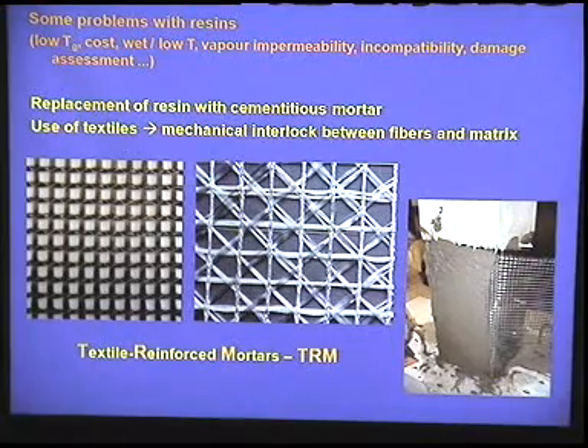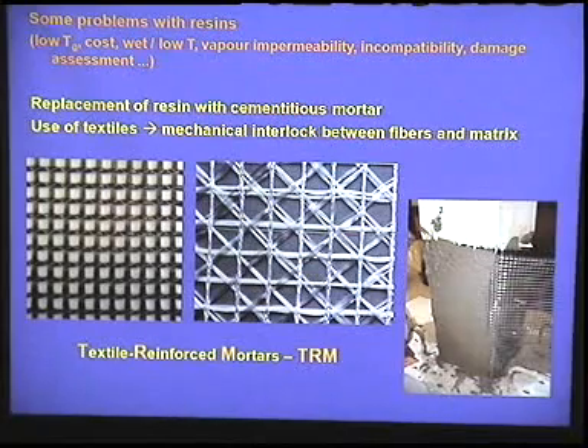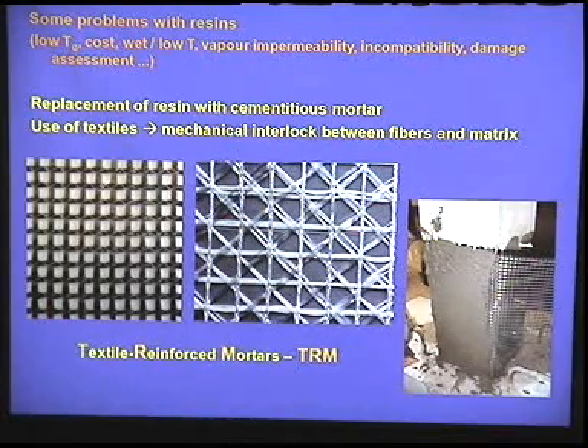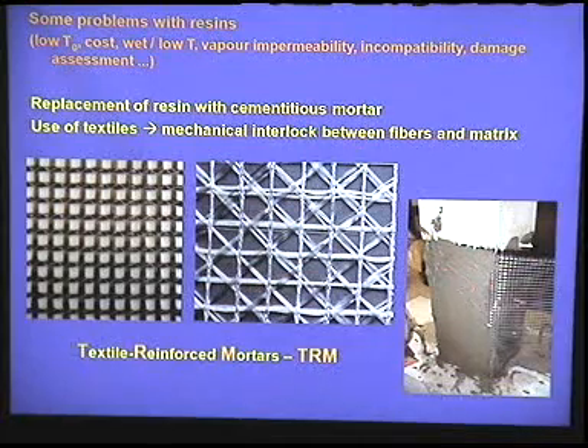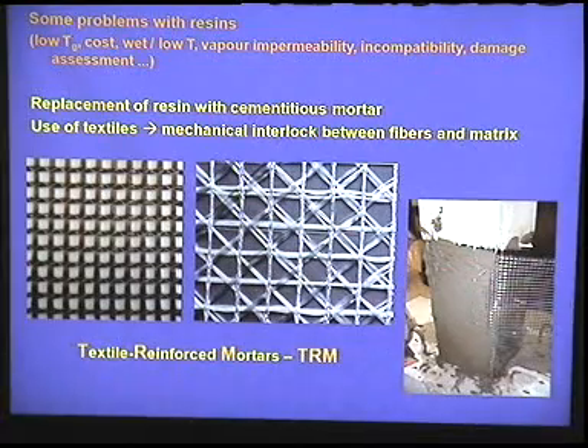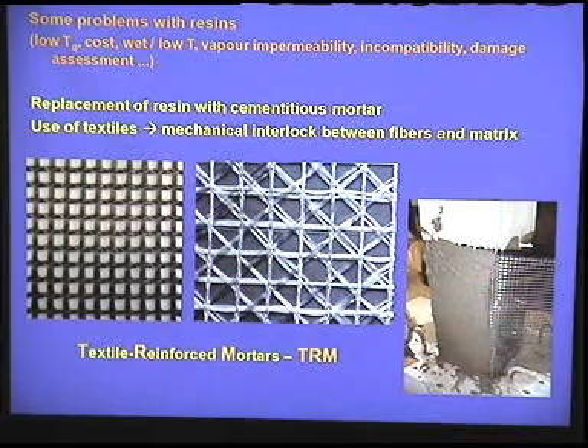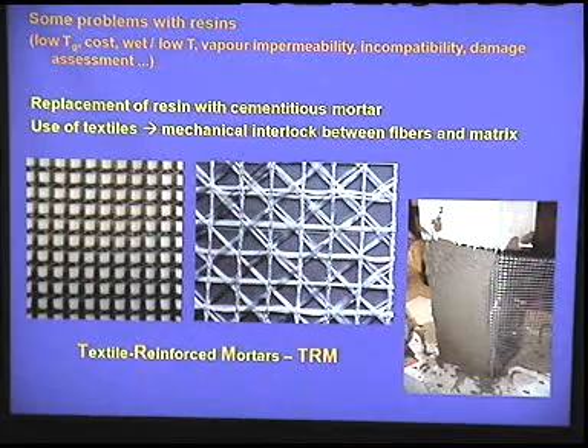To have a good, a meaningful composite, to fully utilize the composite action between the fibers and the matrix, that is the mortar, we need to use the fibers in the form of textiles. So we need an open architecture, a grid-like structure, which is penetrated by the mortar, by the cement or the hydraulic lime mortar, for example. And hence we have the formation of a composite material with very high strength and stiffness that can be used exactly in the way that we use FRPs.